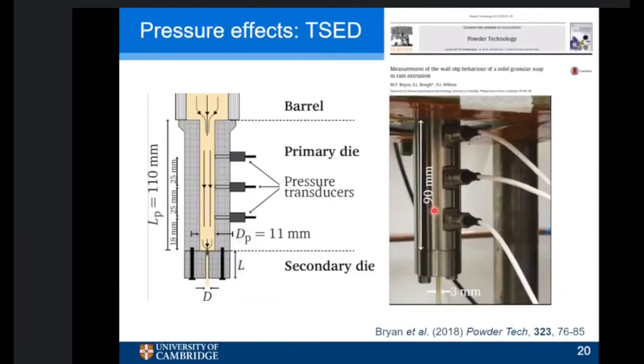So in order to find out if there's any pressure effect, we need to be a bit cleverer about that. And this is something that we did, and Matt Bryan did this, and then Harry Ayton worked on it more recently. I was saying, how do we measure wall shear stress while we want to control the total stress? And this is this thing called a TSED. So this is a secondary extrusion die. And this is what it looks like. So above this thing is a great big plate with a barrel, and that's that bit there. And that extrudes it into effectively a second barrel. So we extrude from this diameter into this diameter, and then we have another diameter at the bottom. We have a secondary die. So we might call this a primary die, and we might call this a secondary die.